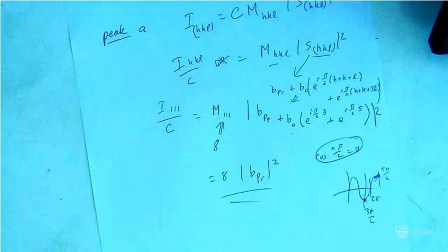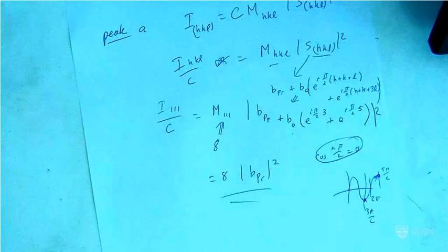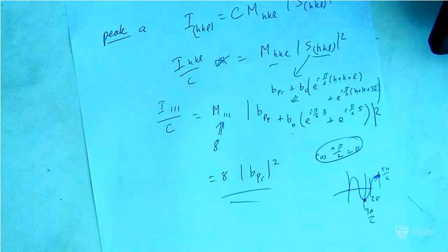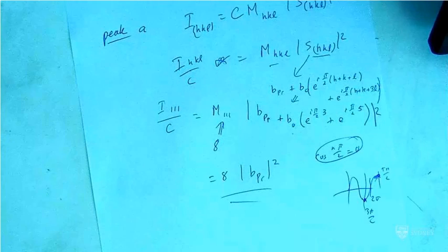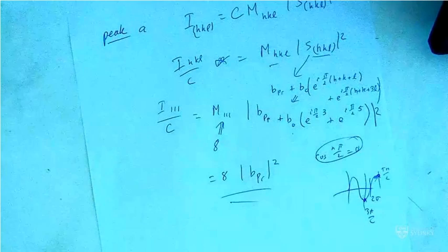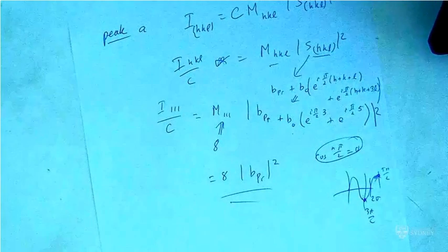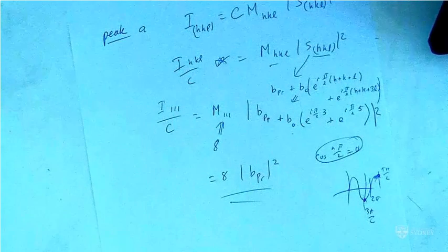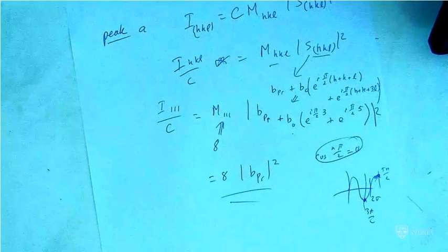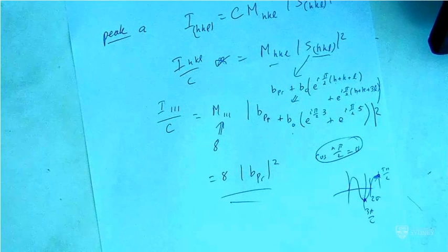For the next one, for B, you do the same thing, except you substitute in 2, 0, 0 for the h plus k plus l up there. And when you do that, you get this expression here. And the same thing for the other one. So you're getting a series of equations from which eventually you'll be able to find the ratio of the scattering length of the praseodymium atom to that of the oxygen atom.